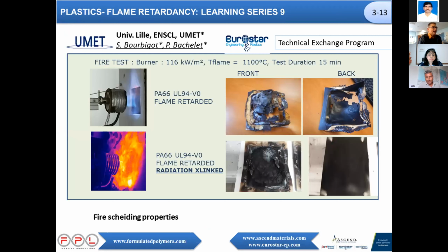This is a slide I added recently just to show you that we are collaborating with a French university for aircraft. They are realizing that aircraft are no more in metal, let's say in aluminum, but more and more in plastics, and they have to shield some pieces against high heat. And here you see, for example, a flame retardant polyamide 66 V0. But here we're not testing a small fire. We are testing a flame of 116 kilowatt per square meter, a flame temperature of more than 1000 degrees C and a duration of 15 minutes.